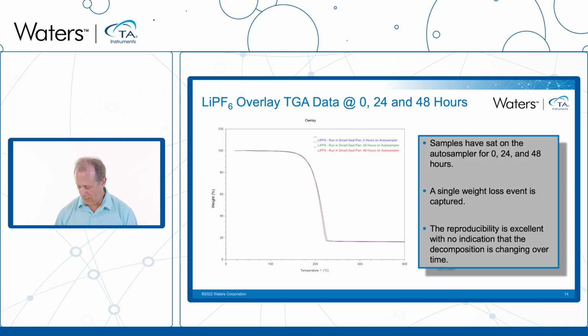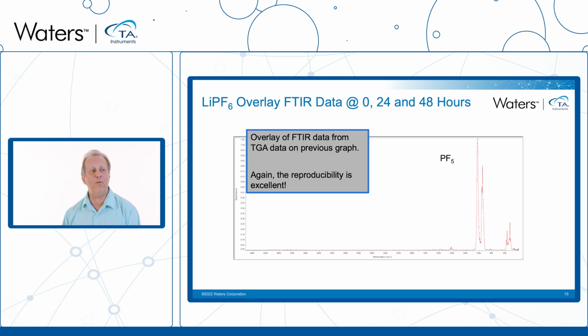And we can further confirm that by connecting an FTIR to the TGA and looking at the spectrum. So this spectrum that's shown here, this is an overlay of all three spectra that are obtained during the maximum rate of weight loss in the TGA scans. We can see the overlay is excellent, and what's captured here is the PF5. So this confirms that this material is dry, and that's all we're seeing here is PF5 being decomposed.